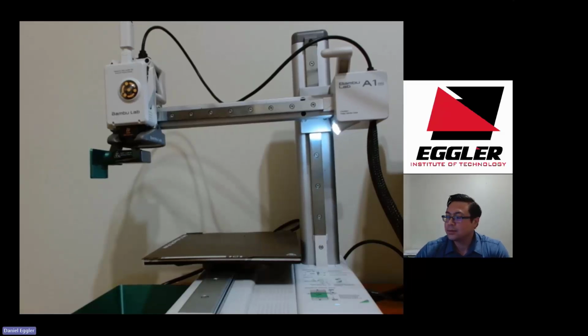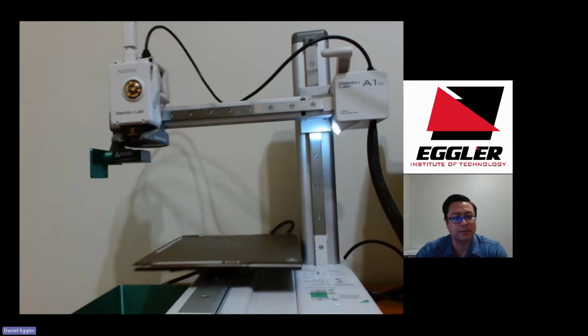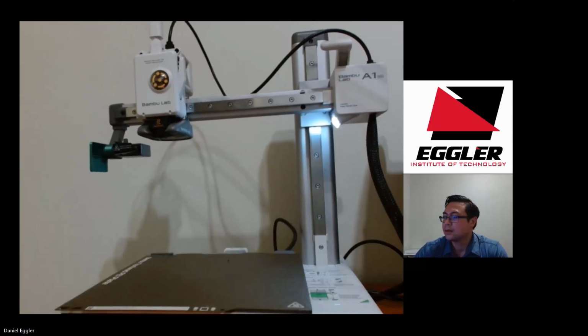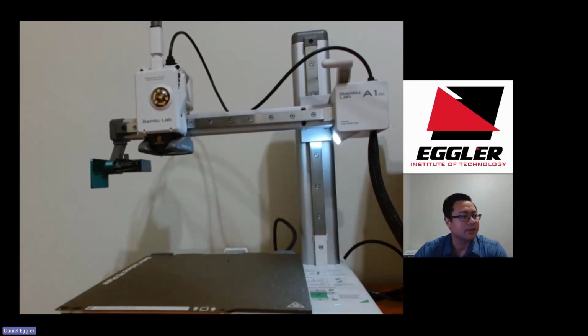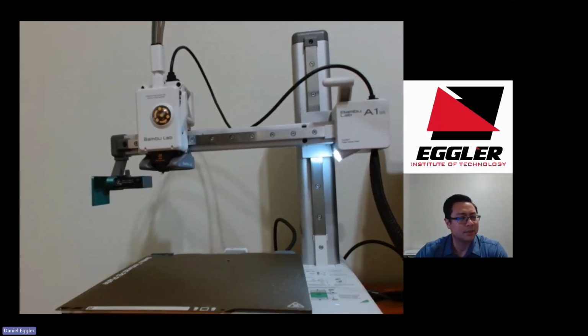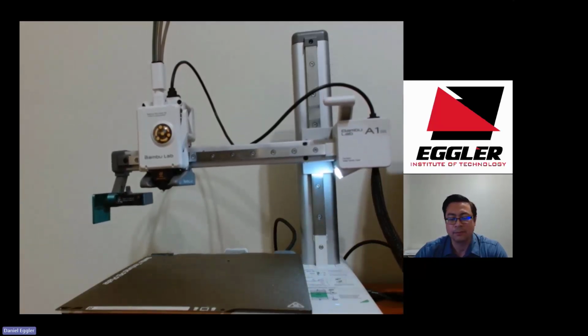If you put the heat chamber too high, you can burn the plastic and cause all kinds of problems where you have burnt residue inside the heat chamber, inside the actual filament reservoir. But this calibration process is quite important. It takes a couple of minutes to run through. It's also going to do a bed leveling.